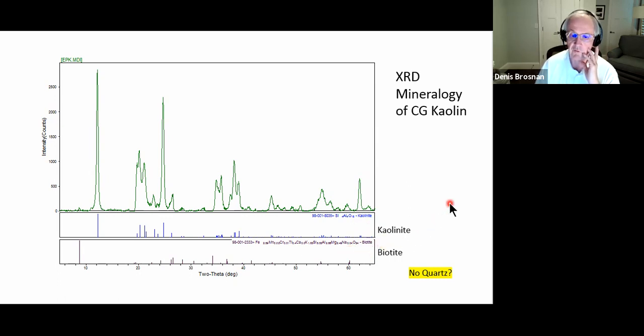Now, you know, mica is a source of alkalis, and so we believe that from the minerals that are present in kaolin, biotite or a micaceous material would be a common impurity in the kaolin. Now, notice that the X-ray diffraction test, which identifies minerals, did not identify any quartz. And that's the good news. And the data sheet for this CG kaolin said that we had less than 1% quartz. So that's why the X-ray diffraction did not identify it.